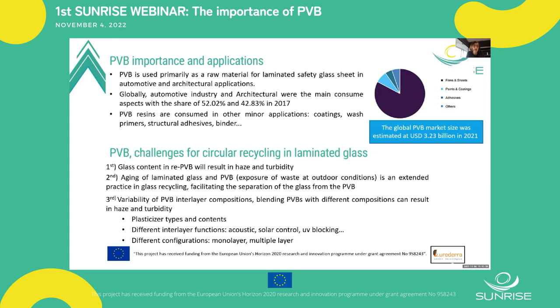And the third challenge we found is the variability of PVB interlayer compositions. We have two points of view here. We have different compositions in PVB, different types of plasticizer, different contents, different layer functions that involve different compositions, and also different configurations. So in terms of compositions, if we aim for a final objective of making PVB interlayers with a mixture of virgin and recycled PVB, we have an issue in terms of mixing the composition. The manufacturer would like to have a PVB composition as similar as possible to the one they are using. So if we mix this PVB, it's not going to be accepted by the manufacturers.